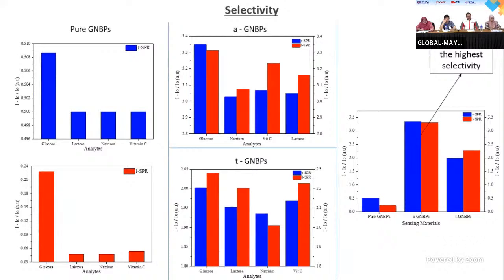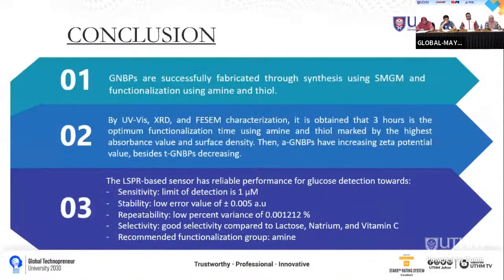Also, from the chart, AGNBPS produces the highest selectivity compared to pure GNBPS and TGNBPS. Even though amine groups can scrape the GNBPS tip and slowly lead to a morphological change, amine groups can increase the selectivity of GNBPS as a sensing material for glucose detection.